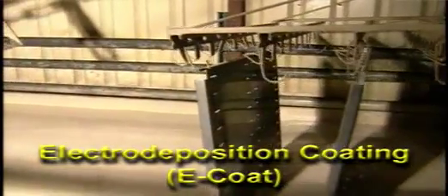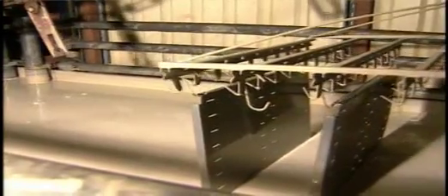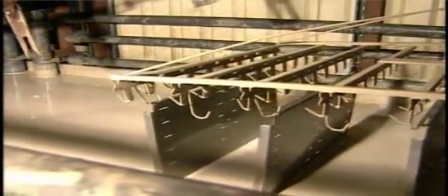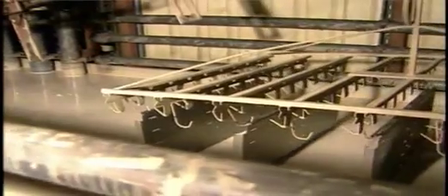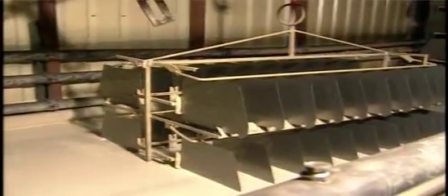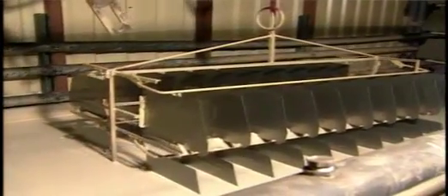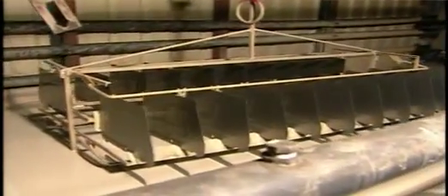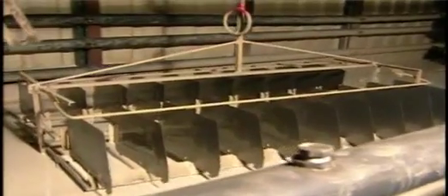In the electrodeposition or EDP process, a DC voltage is applied between the aqueous coating bath and the part to be coated. No solvent carrier is employed. The part, which can act as the cathode or anode, is dipped into the bath. Coating particles are attracted from the bath to the part because they are oppositely charged, producing an extremely even coating. Transfer efficiency for the electrodeposition coating is also typically greater than 95%.